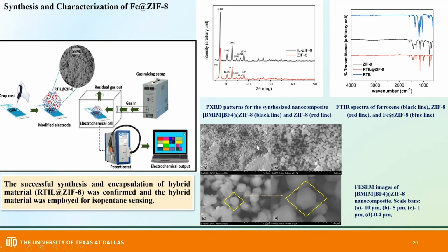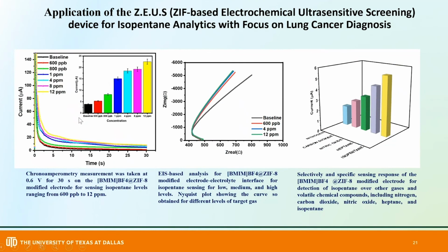After the successful synthesis, we applied it. We used the material for the application and sensing of isopentane. We used chronoamperometry for sensing from 600 parts per billion to 12 ppm, and we saw a dose-dependent response. EIS was used to show low, medium, and high dose response. Again, it substantiated our results that we were able to see increased signal with increased dose response, and the cross reactivity showed the highest specificity for isopentane.